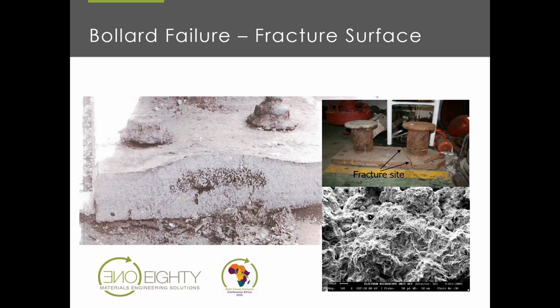On the right-hand side is a scanning electron microscope image of the fracture surface after several years with corrosion on the surface, making it quite difficult to interpret. But nevertheless, it's abundantly clear from the granular form of the fracture surface that the fracture is a result of fast, brittle, catastrophic fracture. So it was an instantaneous fracture that occurred. It was not a time-based fracture. So what resulted in this instantaneous catastrophic fracture is the next question.